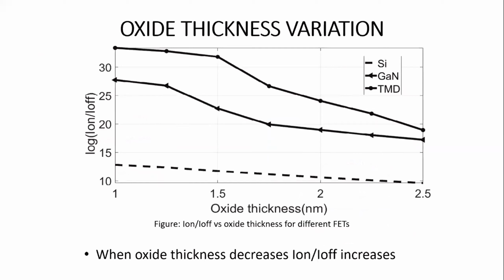Now, here you can see oxide thickness variation with Ion/Ioff. The thinner gate oxide is necessary for the drain current. As a result, the oxide layer thickness needs to be small for a large amount of current. For a smaller value of oxide thickness, a large drain current will shift the value of the threshold voltage of the device to smaller values. Devices with a thick oxide layer have less control of the gate over the channel barrier height.